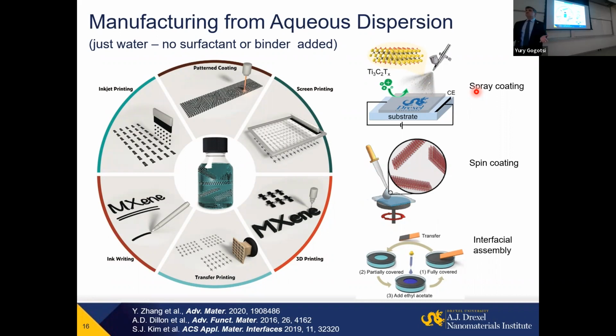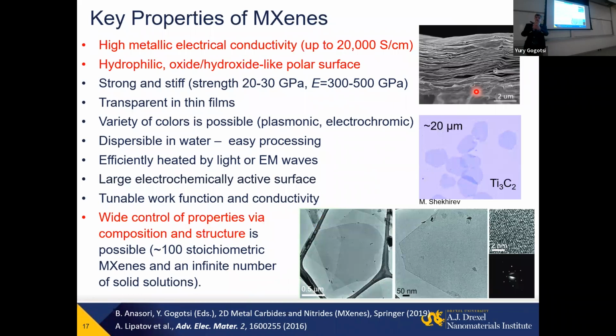Now, if you have a colloidal solution of two-dimensional flakes in water, you can process it the same way as people have been processing other colloidal solutions. There is nothing special you need. It can be inkjet printing, spin coating, dip coating, you name it. It's all easy, straightforward. So we have a huge, enormous family of materials, potentially probably the largest possible family of 2D materials. We can make these materials in large quantities, kilogram quantities in the lab, and actually I'm not aware of anyone making any other 2D material in kilo quantities in the lab. Maybe graphene, but I also don't think a solution of single-layer graphene would be made in kilogram quantities in the lab. And we can process it very easily from water, not just aqueous solution, from pure water, which is plentiful in Canada.